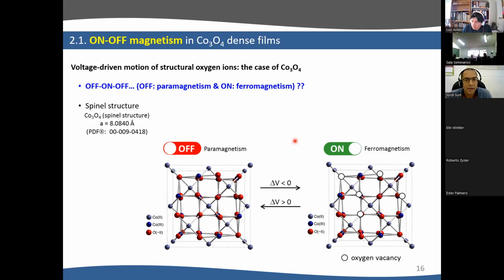First of all, cobalt oxide at room temperature is paramagnetic, at low temperature is antiferromagnetic. And what we want to show here is that we start with a paramagnetic spinel structure. We want to apply voltage to induce the motion of ions, oxygen ions, to the liquid. For example, that was the initial hypothesis, right? To remove oxygen, to create vacancies, and then locally there will be some cobalt-cobalt exchange interaction. So locally, maybe we can generate ferromagnetic response. That was the original idea. Let's see if this worked properly.